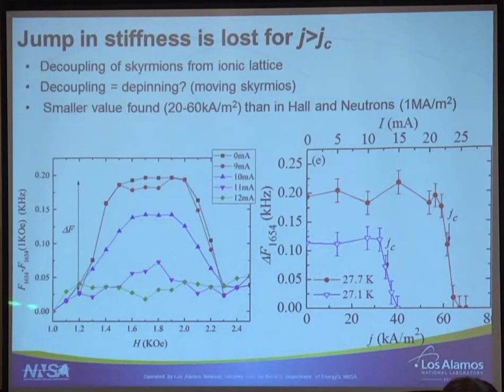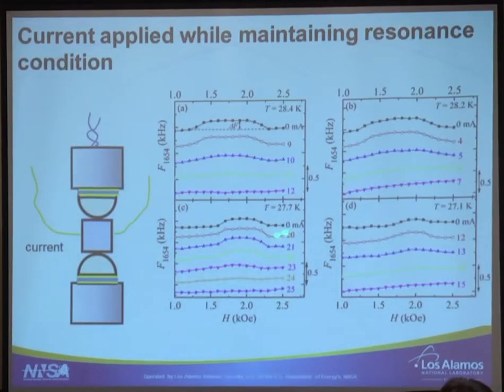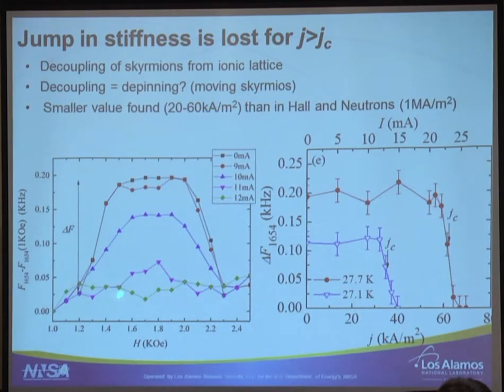So what I did is I just took all this data and set everything to 0 at 1 kilooersted. And this is the data, the same delta F frequency as a function of field. And you see 0 and 9 are basically the same. So whether we put 0 current or 9 milliamps, the stiffening of the system has not changed. However, when we get to 10, 11, 12, this goes down really drastically.